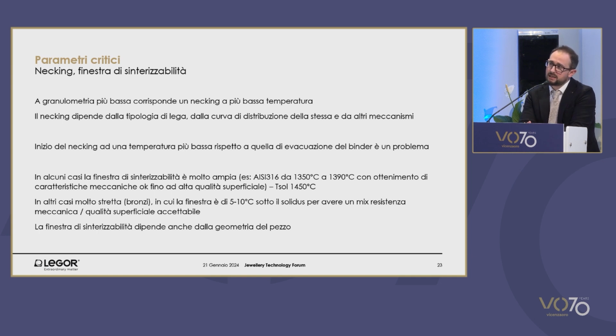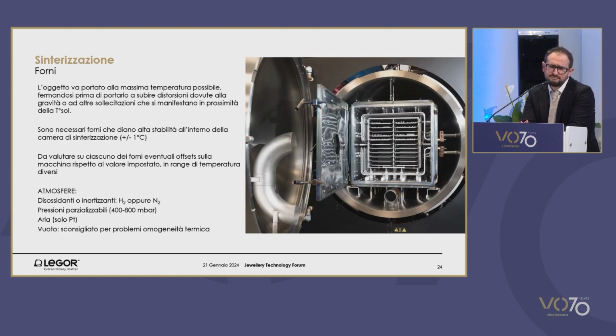On top of that, there are windows of excellent sinterizability that depend on the nature of the alloy. In some cases, they're pretty wide. This is the case of steel. In other cases, they're very narrow, for bronze, for instance, for which the excellent sintering temperature window is very narrow, leading to undesirable results, so that in the lower part, I do not have a good sintering and no mechanical resistance. If I get very close to the solidus temperature, there is the risk of significant distortions.